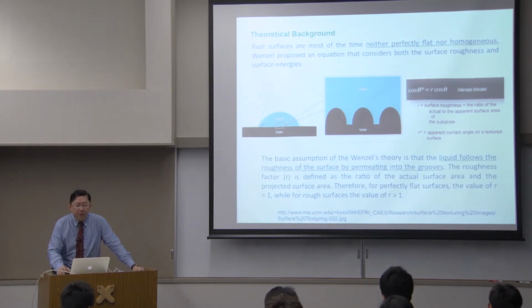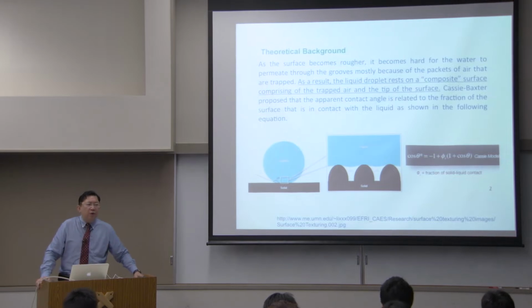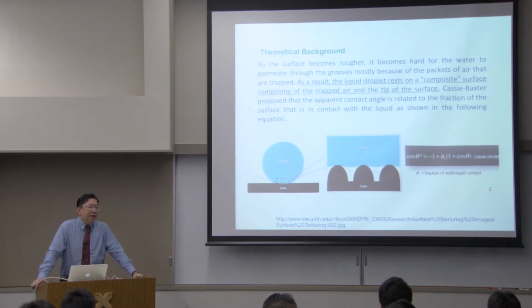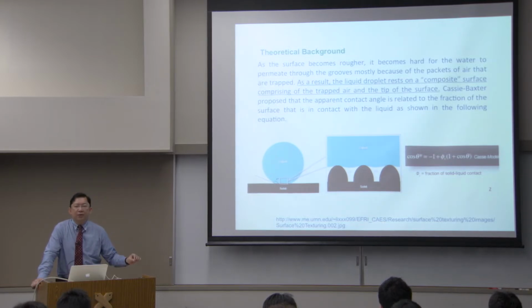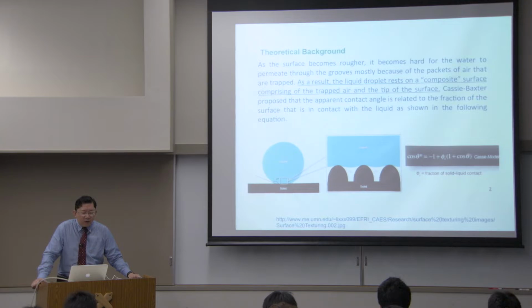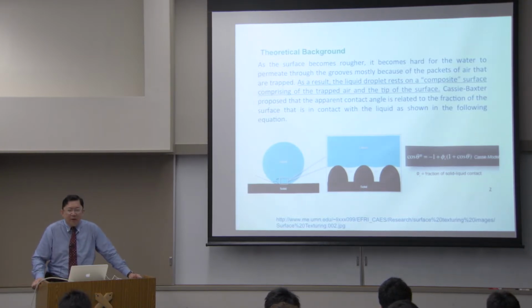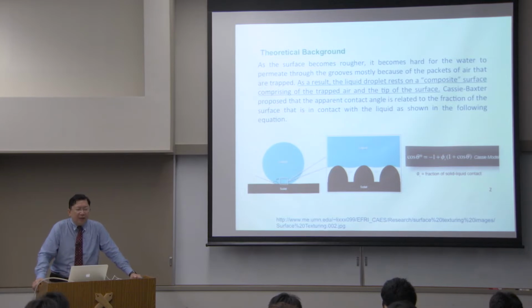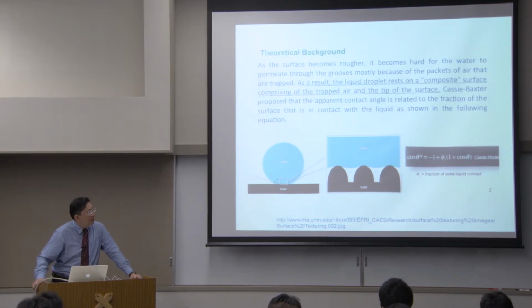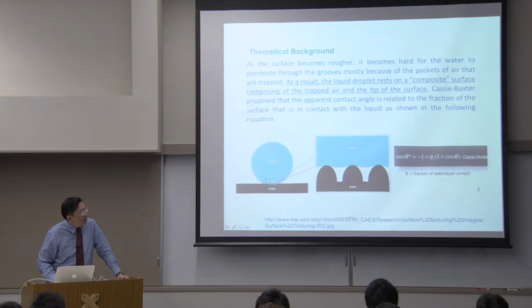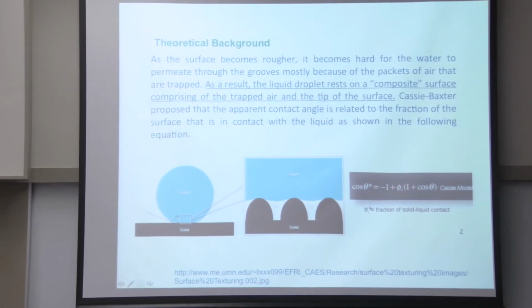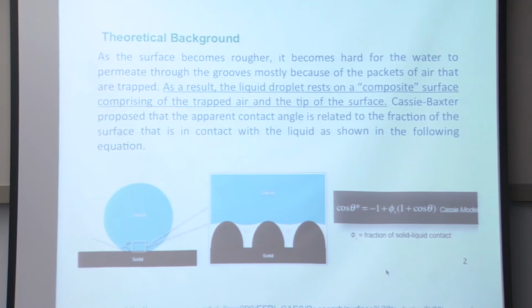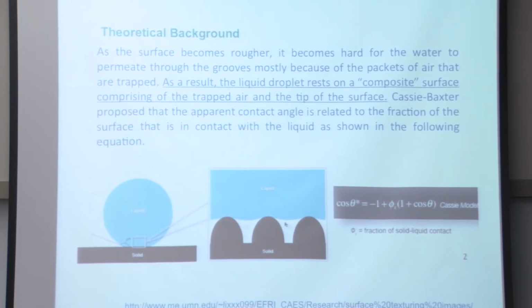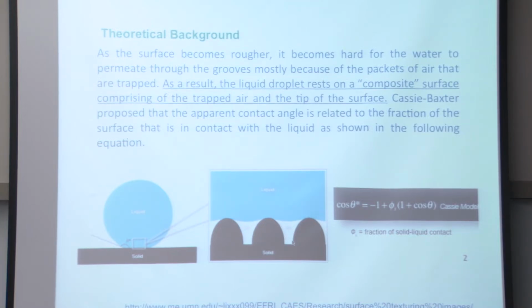The third approach for accommodating wetting behavior is taking that roughness factor and then adding a correction based on trapped air, or volume of air, that prevents the formation of a continuous line tension between the liquid and the surface. That correction can appear here, which essentially is a fraction of the solid-liquid contact lost or accommodated by the volume of air that is trapped in that rough or hierarchical roughness found on a surface.